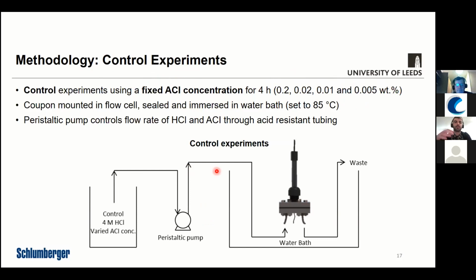And what we would do, we would prepare the carbon steel coupon, mount it within the cell, seal it in with the resin, grind the sample to get the surface finish and smoothness of the whole cell, flushness of the sample sorted, before we would seal it with the gasket, fasten it together with bolts, and then we'd immerse it in a water bath. So this was set to 85 degrees C to account for the heat transfer into the cell and into the tubing, and we validated this previously by using a thermocouple positioned where we would fit the sample. So we would prepare a solution in a beaker of 4 molar hydrochloric acid. We would add the corrosion inhibitor to the acid, use a peristaltic pump to pump the solution through some acid resistant tubing, which would be immersed into the water bath and flow through the flow cell and then out into a waste stream.